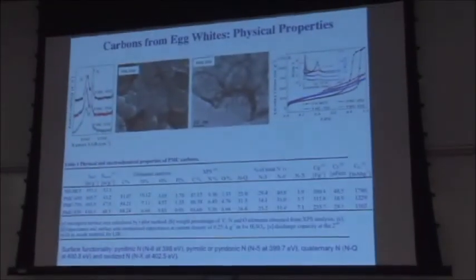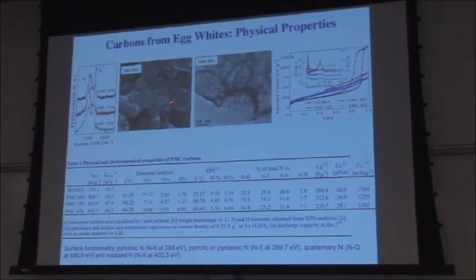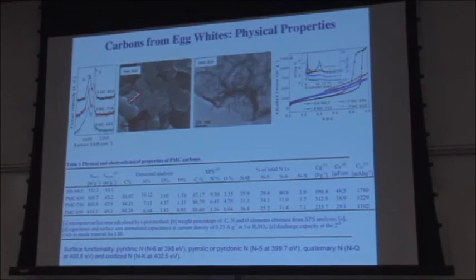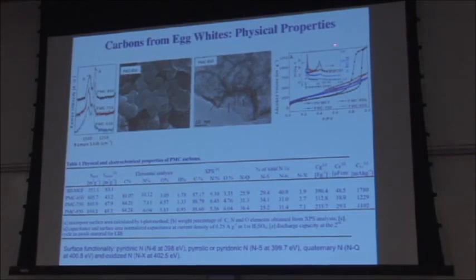If you look at the structure, it's partially graphitic if you compare the G to the D bands in Raman. Macroscopically, it looks like what I call a caramel corn morphology, so it's popcorn that's interconnected. If you look at the TEM micrograph, you clearly see the large pores. You actually can't really see the small mesopores that are about 3 to 5 nanometers in diameter. We confirmed this. We got the surface area using both DFT and BJH methods, I believe. So you have a bimodal pore size distribution with a peak near 3 nanometers, and another peak that should really be about 20 to 30 nanometers, and it's a bit shifted because of how the modeling gets done.